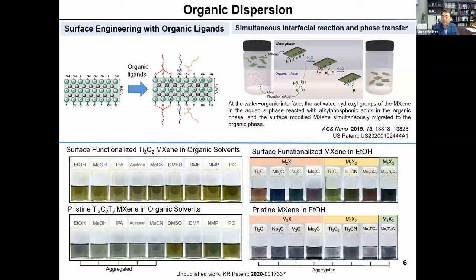Recently, we developed a more efficient method, not yet published, to surface functionalize MXene flakes. The MXene organic dispersions prepared through this method are very stable in various organic solvents, even at very high concentration. As you know, the color of a dispersion is a useful indicator of good dispersion. For example, Ti3C2 MXene well dispersed in an organic medium on a single sheet scale shows this kind of clear greenish color. As you see, the surface functionalized MXene reveals a clear greenish color in various organic solvents, indicating that the functionalized MXenes are well dispersible in various organic solvents, especially in non-toxic organic solvents such as methanol and IPA, isopropanol. Other types of surface functionalized MXenes are also very well dispersible in various organic solvents.